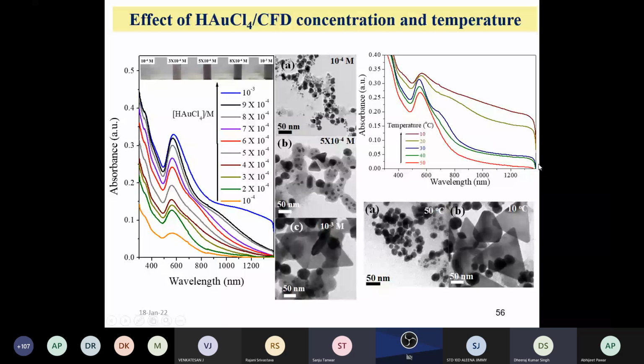It means that if you correlate the TEM image with this UV visible, then in the TEM image you are seeing triangle types of, means non-isotropic particles are also formed during the synthesis of anisotropic gold nanoparticle. You can see that because it is directly connected to here. At 50 degree, no peak in NIR region, means only spherical, dominant spherical particles are there. But in this part, triangle particles along with spherical particles are also coming, where you can see UV visible and TEM are directly connected. And one more conclusion you can draw: higher concentration of your molecule showing the anisotropic property, and higher temperature showing spherical particles, and lower temperature showing the triangle types of nanoparticle.